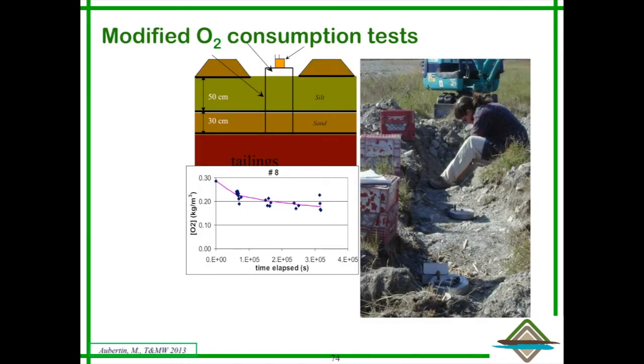I said that we also developed techniques for measuring oxygen diffusion. This is an example with Anne-Marie Dagenais, who did her PhD a few years back on this technique. Using these probes in the field that we insert in the cover, we can measure the flux of oxygen and back calculate the diffusion coefficient and the efficiency of the cover. This has been published.